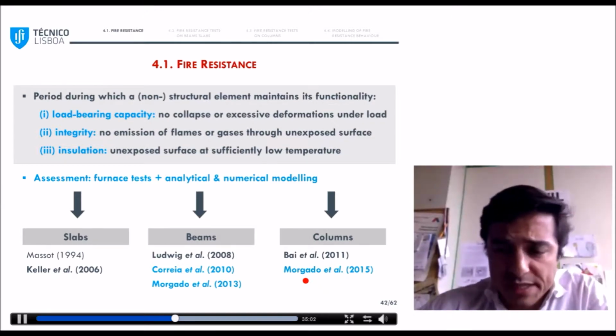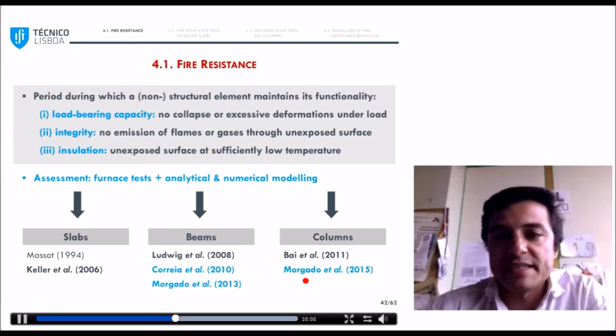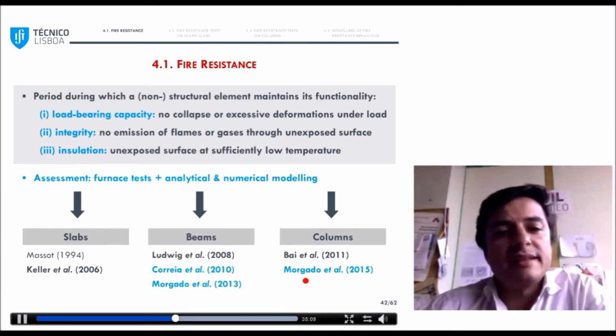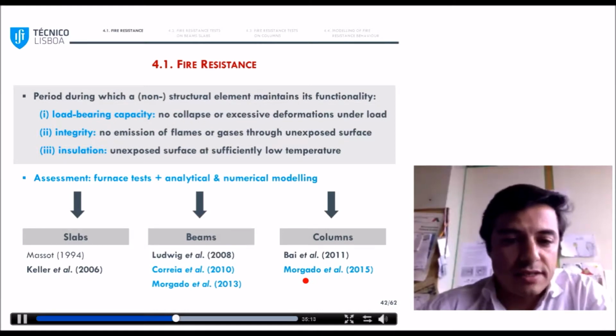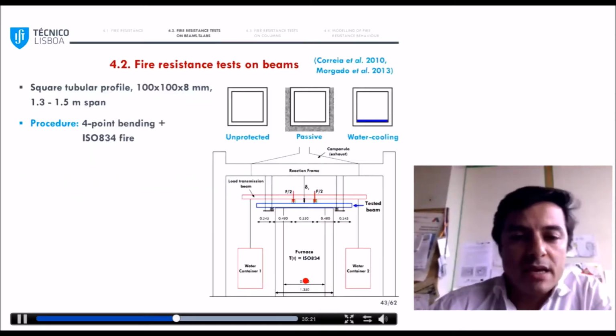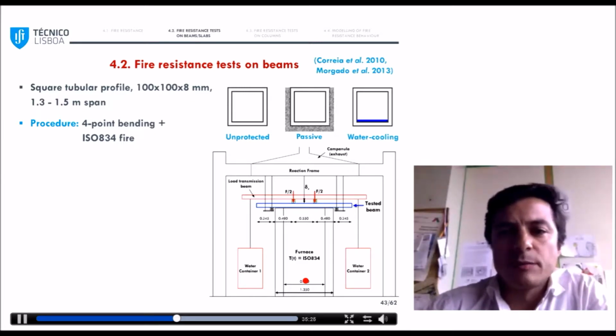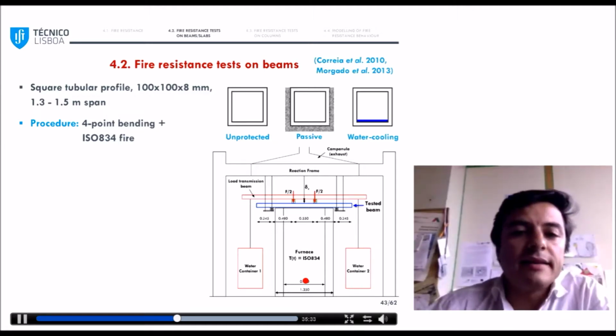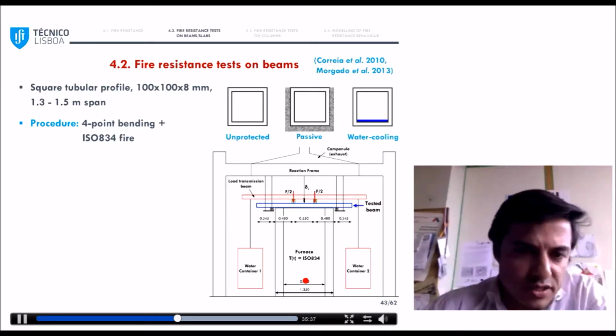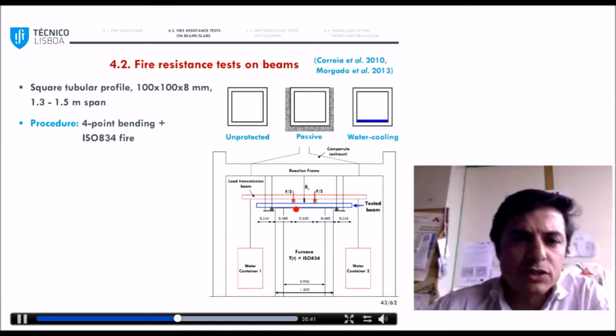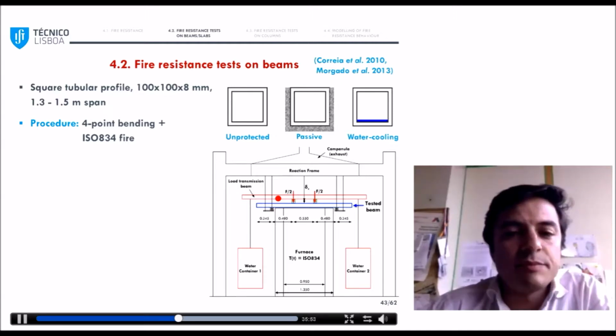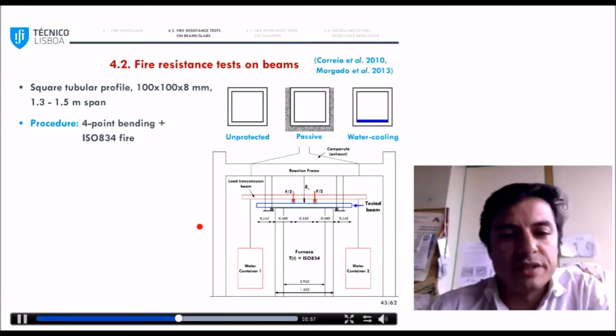So in the next slides, I will describe results obtained from furnace tests or fire resistance tests on slabs, beams, and columns, and at the end, the corresponding modeling of these experiments. So at IST, we did a quite comprehensive experimental program on the fire resistance of tubular beams. They were tested under 4-point bending, and they were exposed to the ISO 834 curve, which is a standard fire curve. Here you can see the setup. So this is the furnace we used. The beams were placed on top of the furnace, and they were loaded with 2 water containers, which is a quite convenient system because you know that the load will be kept similar during the test.